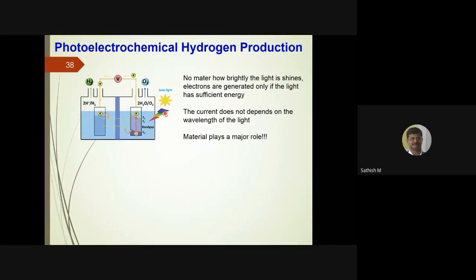So, the only main condition is the light has sufficient energy. That means that the energy of this light should be higher than the band gap energy of the semiconductor. Okay, otherwise it will not get excited. Also, the current does not depend on the wavelength of the light. It depends on the intensity of the light. For example, if you provide a sufficient wavelength light with high intensity, then obviously the current moving through this external circuit will be higher.